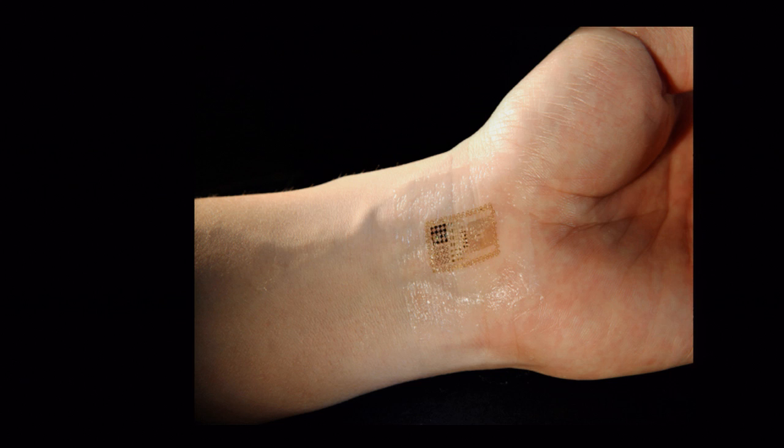This is an earlier device with water-soluble PVA as the carrying substrate. The elastomeric substrate is only about 30 microns thick, and the electronics layer is even thinner — less than 7 microns. So this is thinner than a Band-Aid by far. You can think of this as a temporary tattoo — applied in exactly the same way — but now you're able to deploy electronics on the body.